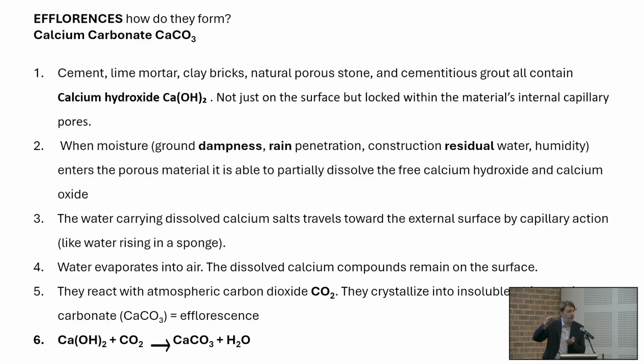And when it arrives on the surface, the water will evaporate and will meet CO2. Will meet the air here. You see? Once the calcium hydroxide meets the air, they become calcium carbonate. Not soluble with water, not easy to remove, special cleaner to remove, and we have the white spotting on the surface. So the problem is not the cement, the substrate, it's water.